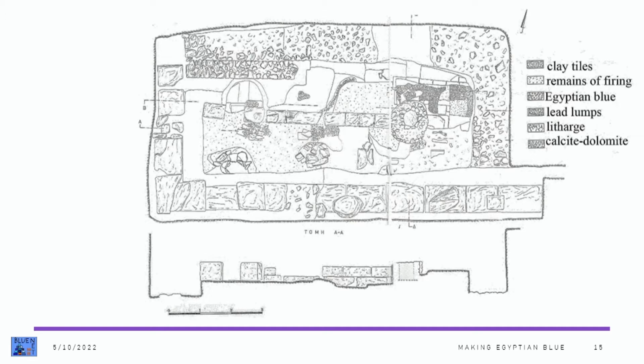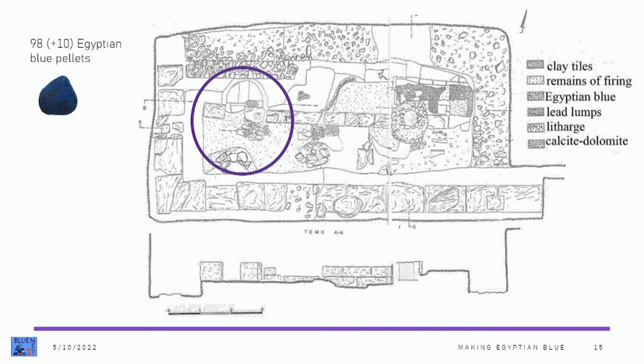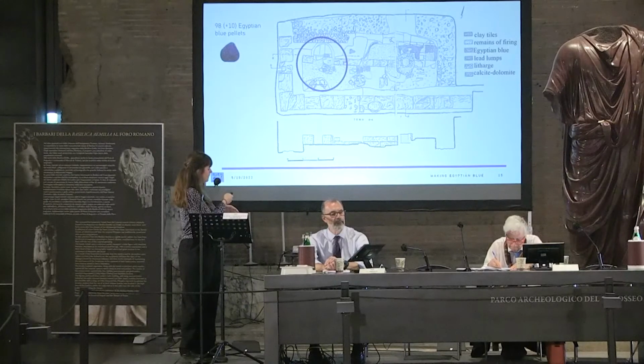Is there? Yeah, okay. At least 2 fire structures were identified at the site, one here and one here, most probably more, but in a very destroyed state. And in the westernmost fire structure, about 98 Egyptian blue pellets were found inside the pit, the fire pit.